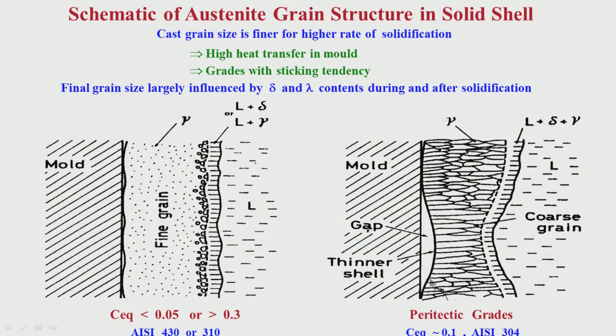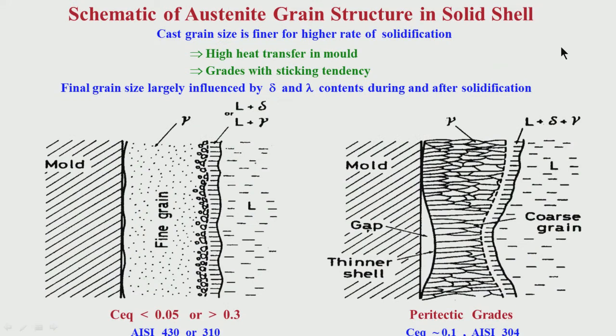The same thing I am trying to explain here schematically through the austenitic grain structure in the solid shell. After solidification, beyond a certain temperature, when we are cooling to lower temperature, finally all grades will become austenite irrespective of the chemistry, but the solidification mode is somewhere delta, somewhere delta plus gamma, somewhere only gamma austenite. So, a certain chemistry range, as I have told you, will give you depression tendency, and certain chemistry will give you sticking tendency and bulging tendency below the mold and sticking tendency inside the mold.